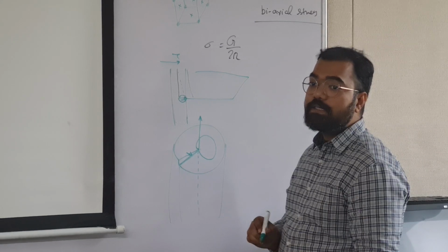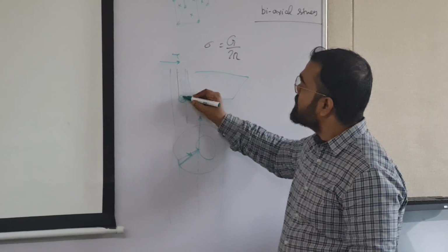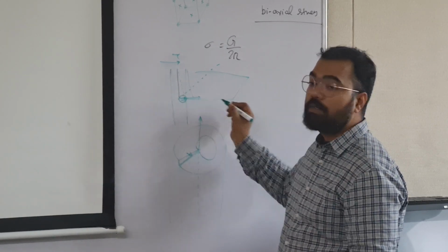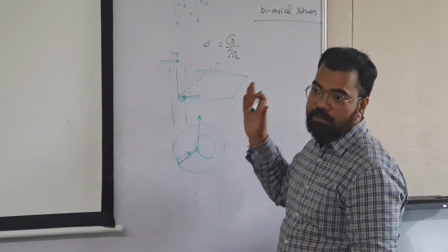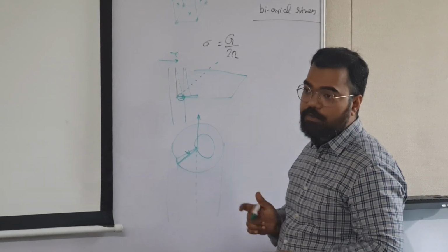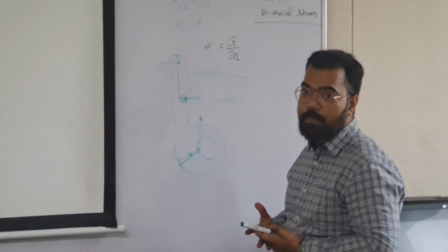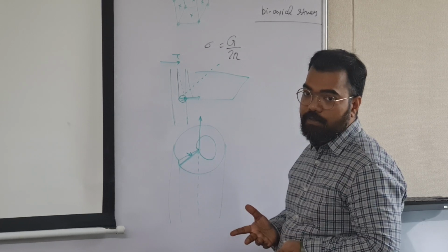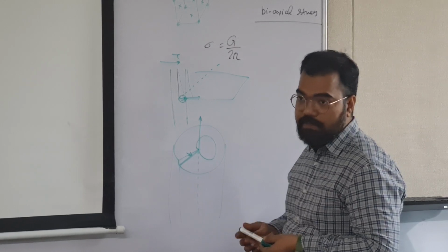So what is different in this case in comparison to that one is that in this case the line of dislocation is this and the movement is in this direction, so it is perpendicular to the line of dislocation. In this case it is parallel. Because of this behavior, screw dislocations have least resistance in movement, because they don't need a plane first of all. So that requirement is not there, so that makes their movement very easy.